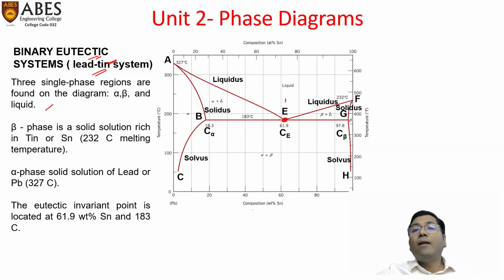So here this liquid L would be converting into alpha plus beta, two different solid phases, at 61.9% composition, that is called CE, and at a particular temperature, that is 183 degrees Celsius. This is for the particular lead-tin system which we are considering. So eutectic reaction means one liquid phase is converted into two different solid phases. Here three single phase regions are found on the diagram: alpha, beta, and liquid. Alpha and beta are two separate solid phases, and also liquid.